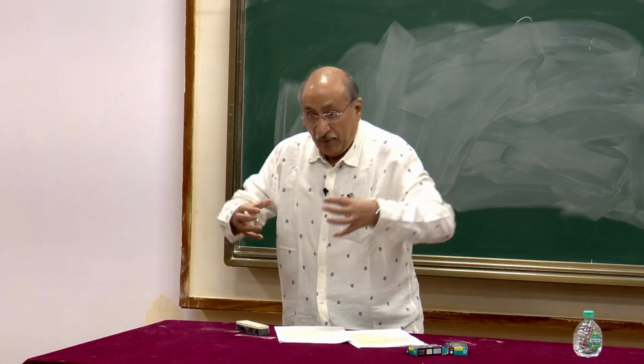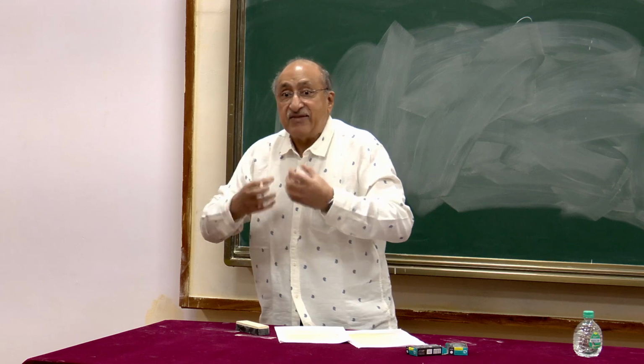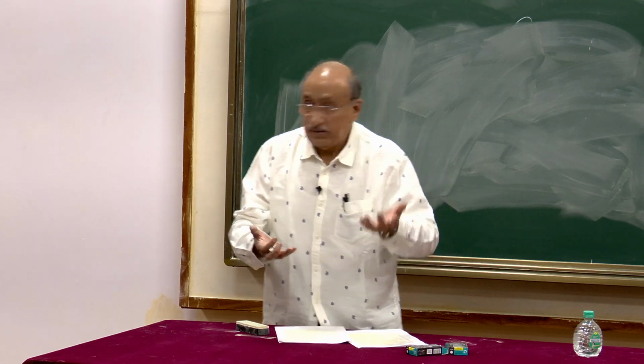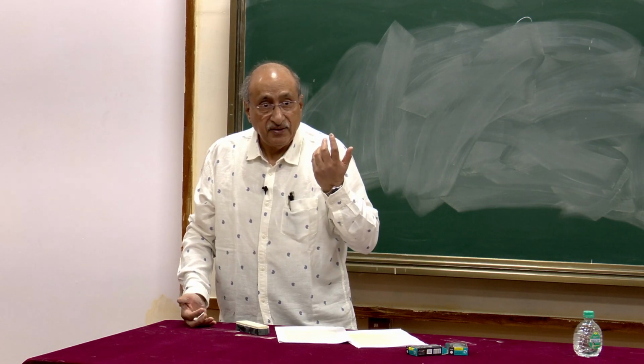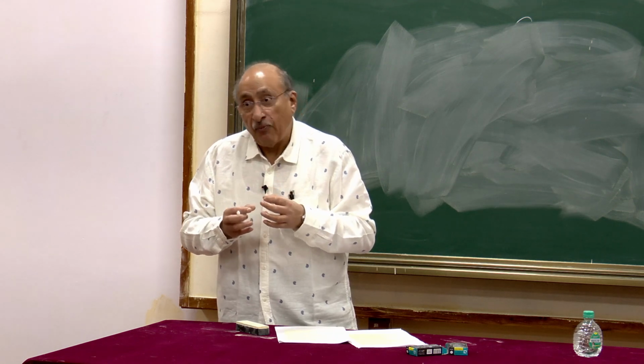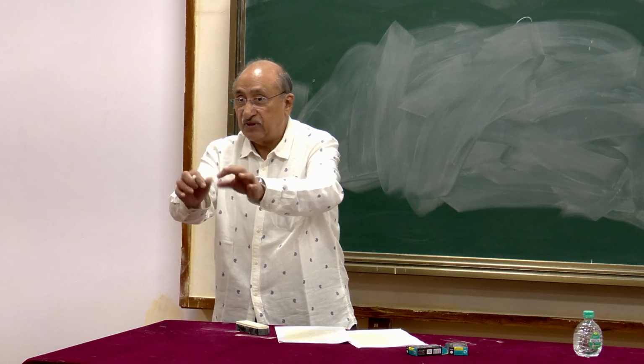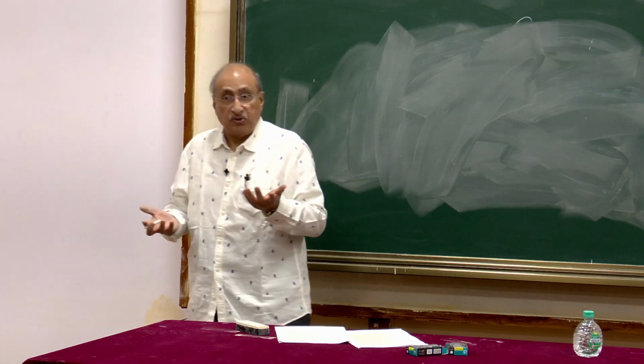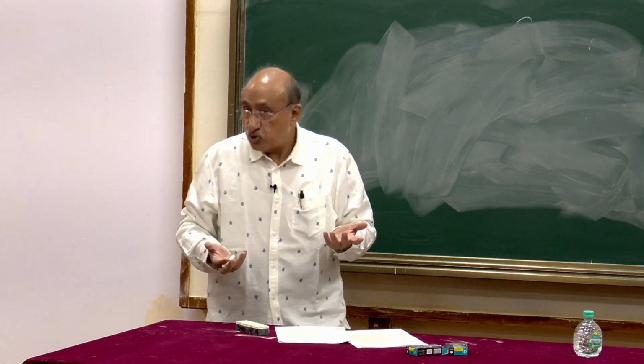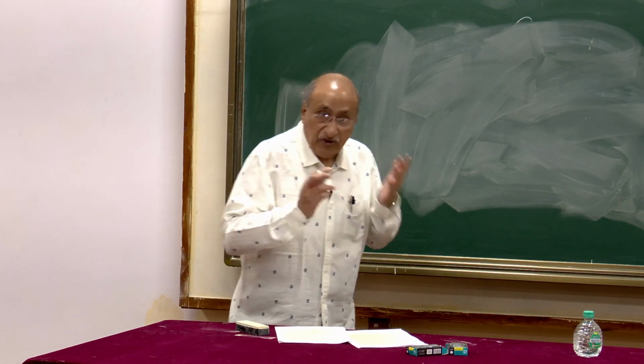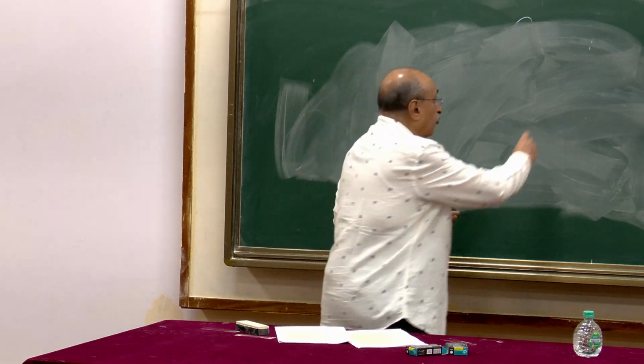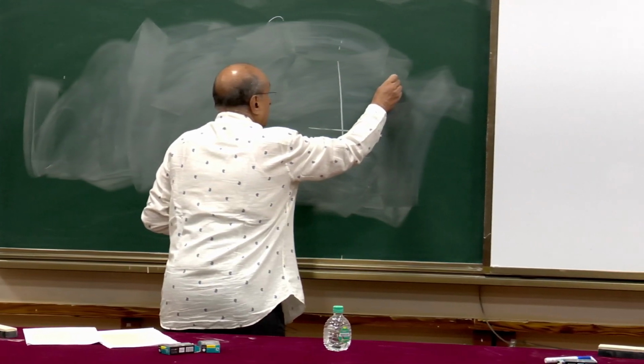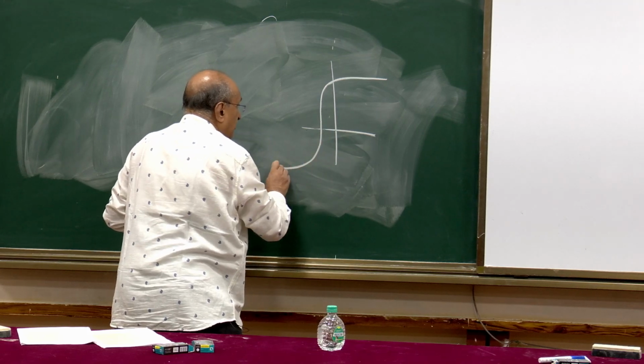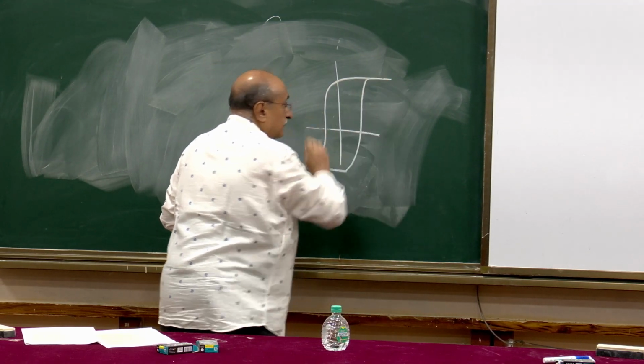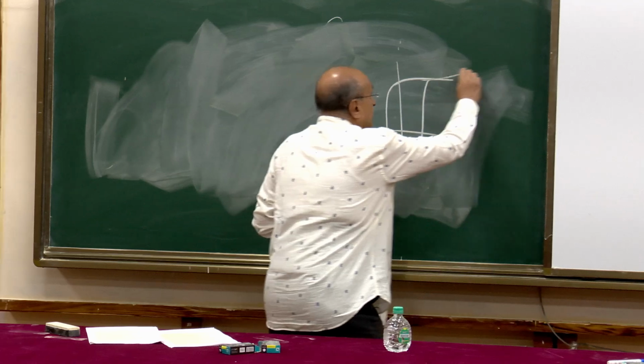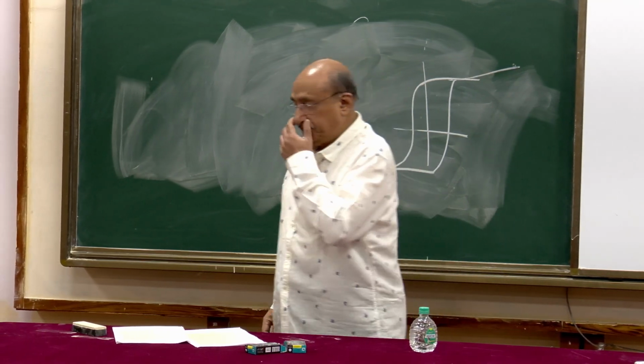But remember, if I keep on making grain size smaller, for which there was a need, I had mentioned it yesterday, I am always going to increase the grain boundary volume ratio. So I have to take care of that also. In fact, one of the things which most of the time happens is that if you measure an MH loop, in which in bulk you see very nice saturation, in thin films it keeps on increasing. It does not show saturation.